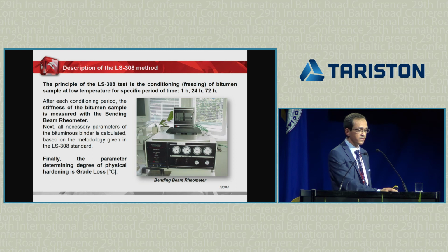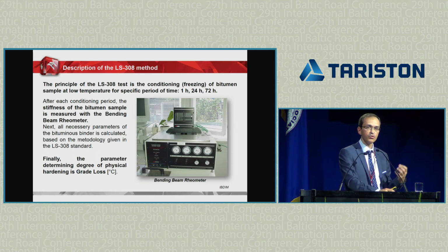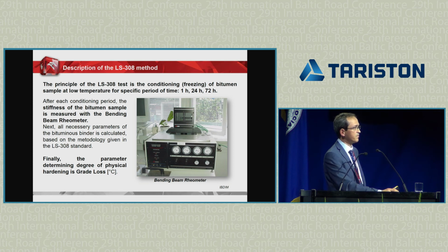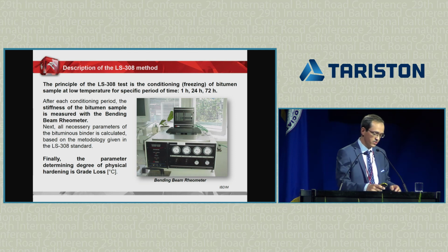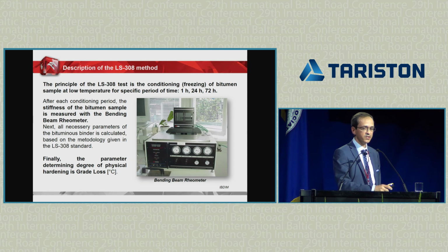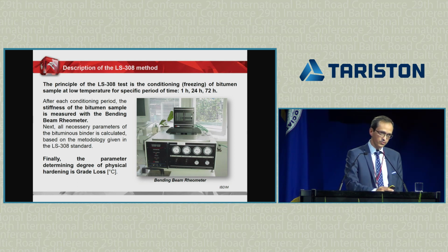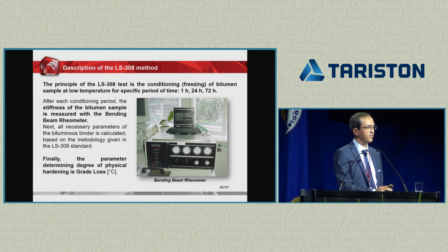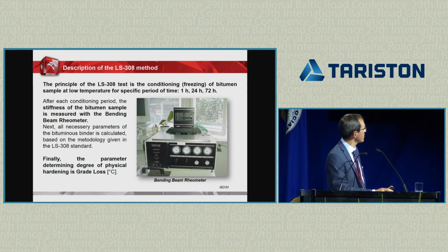But in addition to this typical test, we introduced to this test a freezing, conditioning period. And after a specified time of this conditioning period, especially after 1 hour, 24 hours, 72 hours, the stiffness of the samples is measured, and then based on calculations which are described in detail in the standard, we can calculate the final assessment of the binder, which is called grade loss.